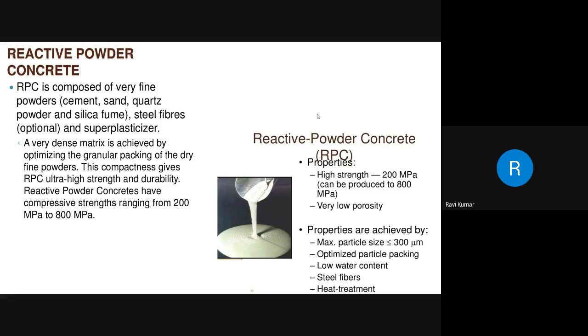This RPC has compressive strength ranging from 200 MPa, that is 200 Newton per square millimeter, to 800 MPa. The properties of RPC are high strength and very low porosity. These properties are achieved by using a maximum particle size less than or equal to 300 micron, optimized particle packing, low water content, steel fibers, which are optional, then heat treatment. I tried to bring the pictorial representation of RPC concrete.